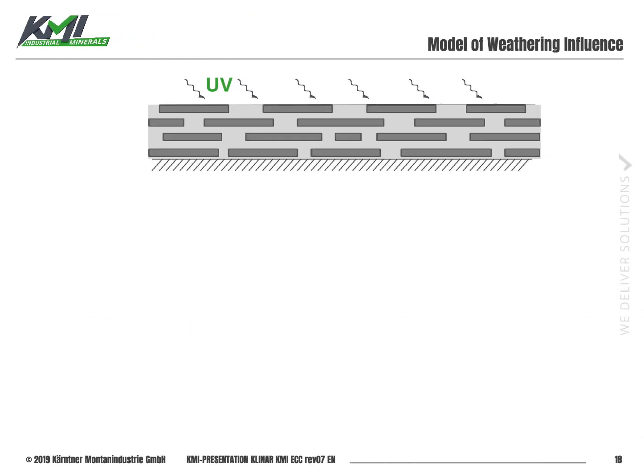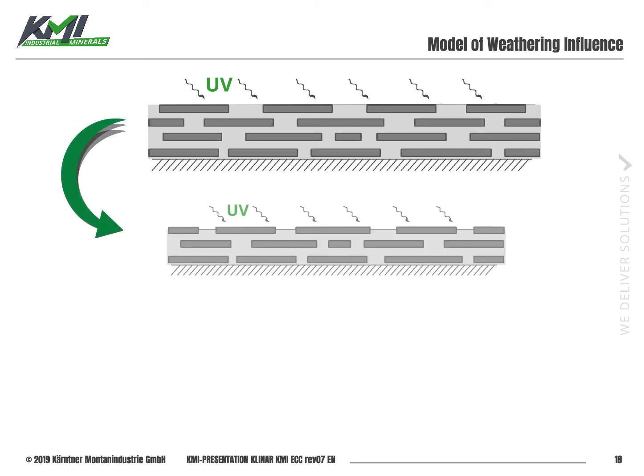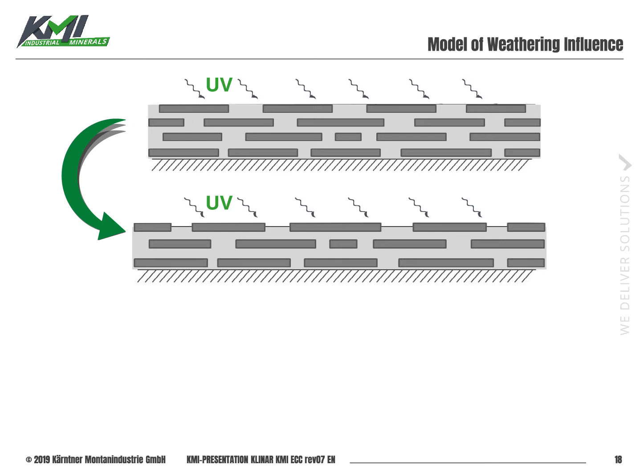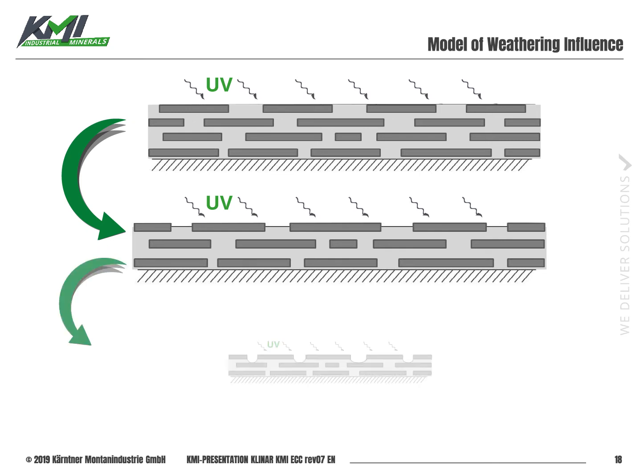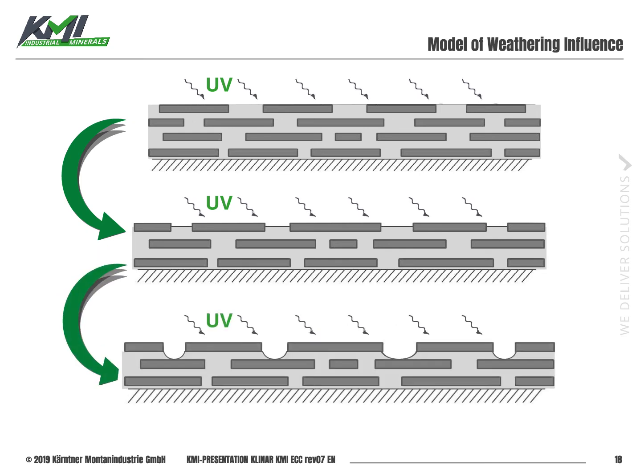When you compare it with a more lamellar type of micaceous iron oxide, you will see the same effect at the beginning, so you will lose the first layer of resin in between the platelets. But due to the fact that you have platelets and you still have a good adhesion on the resin, you will end up finally with a layer of micaceous iron oxide platelets overlapping on the top, absorbing and reflecting every kind of radiation and protecting the resin against degradation.